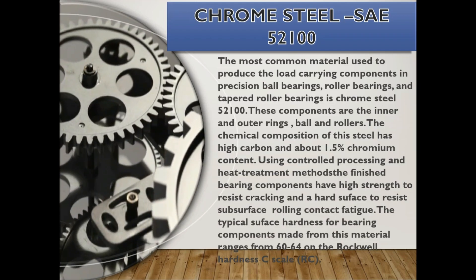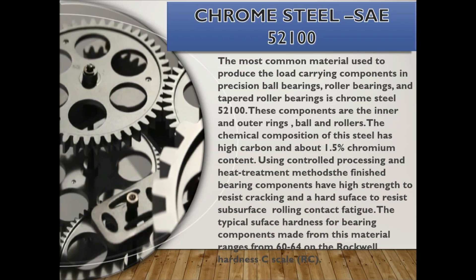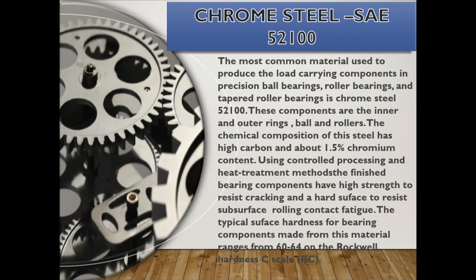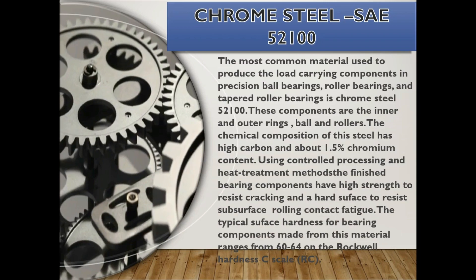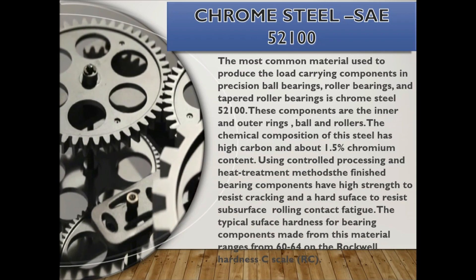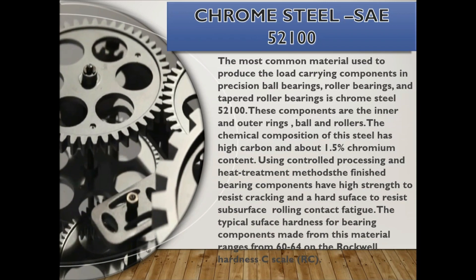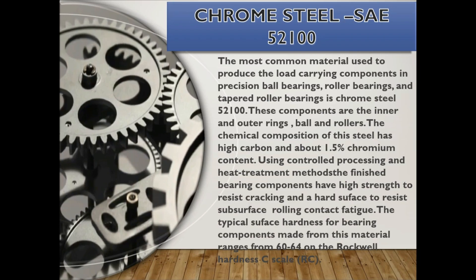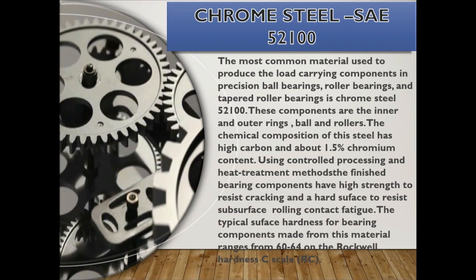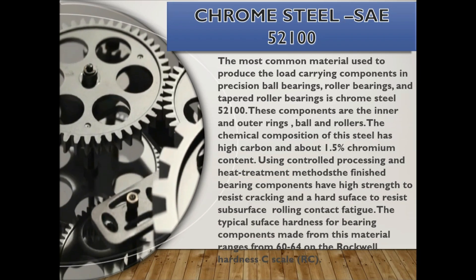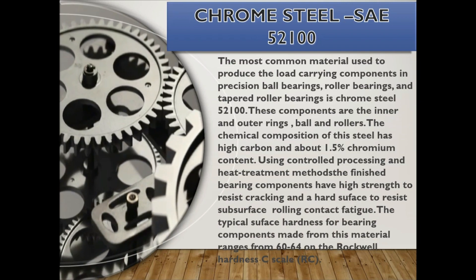Using controlled processing and heat treatment methods, the finished bearing components have high strength to resist cracking and a hard surface to resist subsurface rolling contact fatigue. The typical surface hardness for bearing components made from this material ranges from 60 to 64 on the Rockwell hardness C scale (RC).